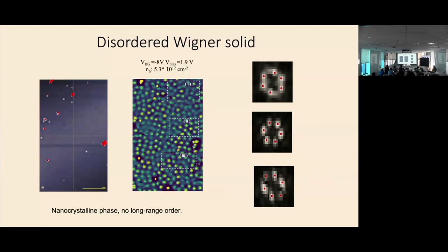So I think people are still trying to figure out exactly what defects are there. But the oxygen replacing sulfur or selenium seems to be a common thing that is present. Okay, and then if we start to dope holes into the system, what we can see is all these charge densities are rather localized. They are very spotty. So that led us to think these are more like a solid behavior. The electrons are really rather well localized at specific points rather than like an electron liquid where they are more spread out and homogeneous.